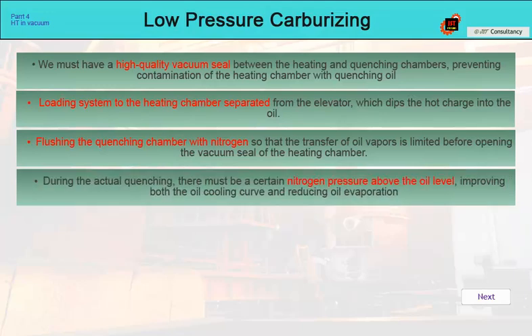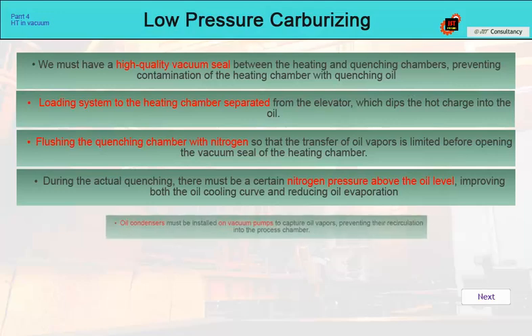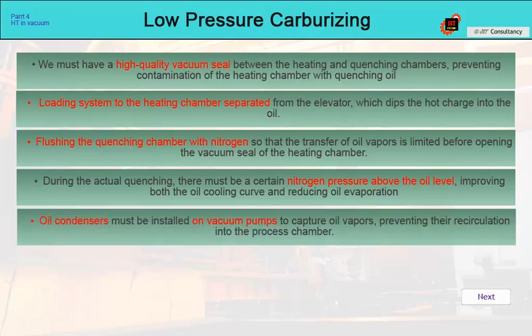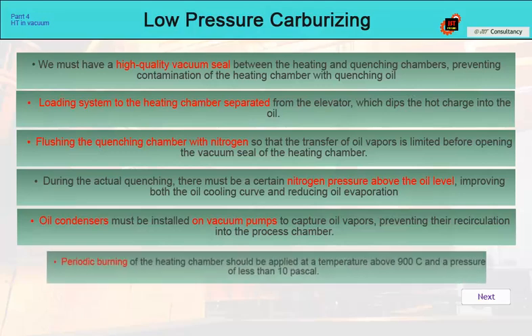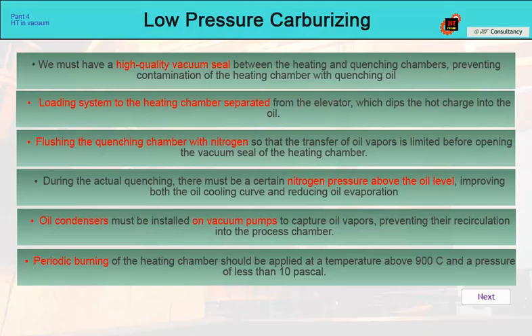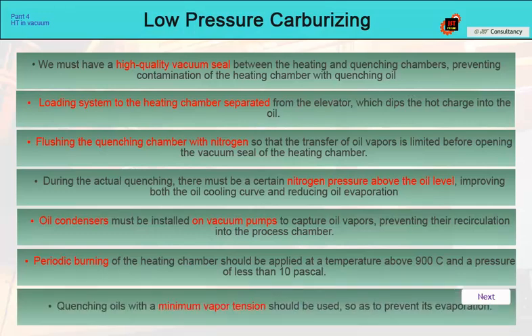During the actual quenching, there must be a certain nitrogen pressure above the oil level, improving both the oil cooling curve and reducing oil evaporation. Oil condensers must be installed on vacuum pumps to capture oil vapors, preventing their recirculation into the process chamber. Periodic burning of the heating chamber should be applied at a temperature above 900 degrees Celsius and a pressure of less than 10 pascals. Quenching oils with a minimum vapor tension should be used so as to prevent its evaporation.